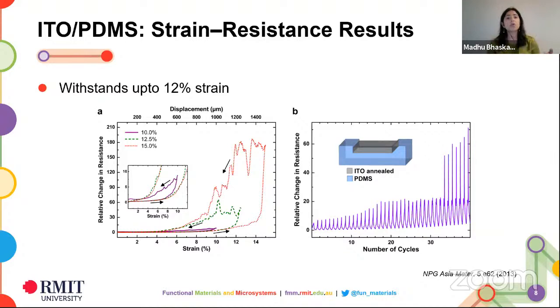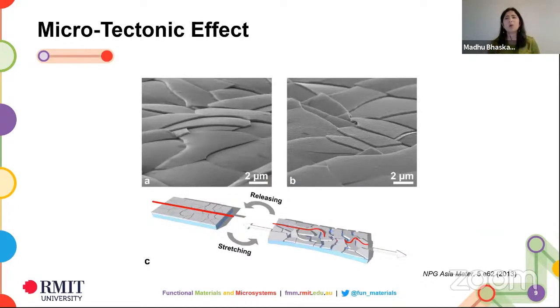But once you let it go and it went back to its original 0% strain, it kind of recovered its resistance properties. So we were quite surprised to see this happen. We did a number of cycles. These were very initial results from 2013, but since then, the performance has been significantly ramped up. And we were trying to understand how is it that indium tin oxide, which is extremely brittle, is now able to withstand strain up to around 12%.